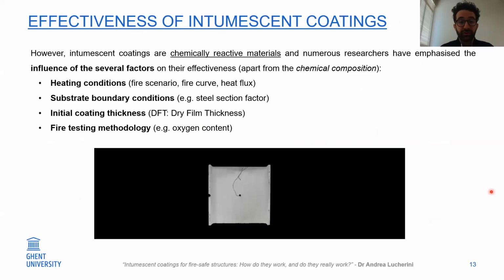However, researchers and people in the field know that intumescent coatings are chemically reactive materials, and numerous researchers have emphasized the influence of several factors on their effectiveness. So apart from the chemical composition, what we can expect is that the performance of intumescent coatings exposed to fire is influenced by several factors. The first one would be, for example, the heating conditions. So for example, the fire scenario, the fire curve, or the heat flux applied on the coating, the substrate thermal conditions, for example the steel section factor that I just mentioned earlier, the initial coating thickness, which I mentioned earlier as the dry film thickness, and the fire testing methodology. For example, the oxygen content in your testing apparatus.